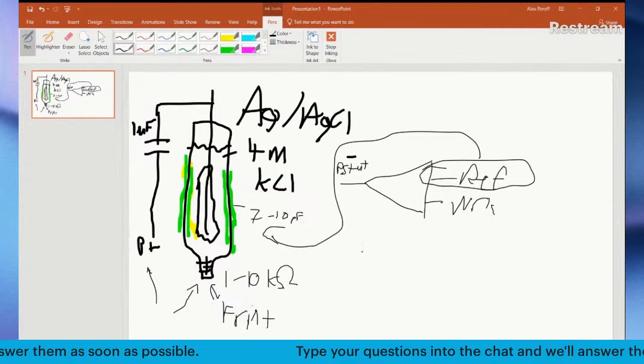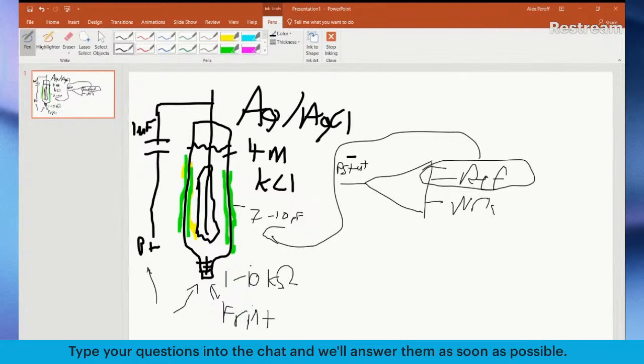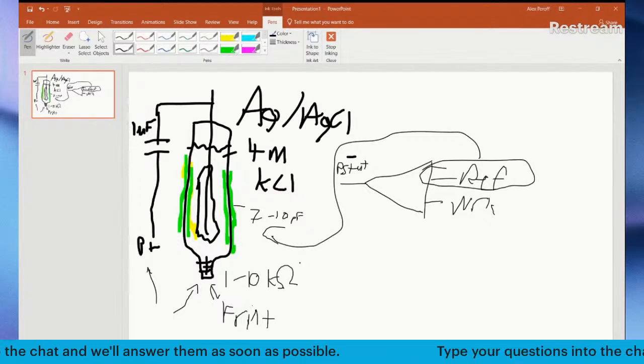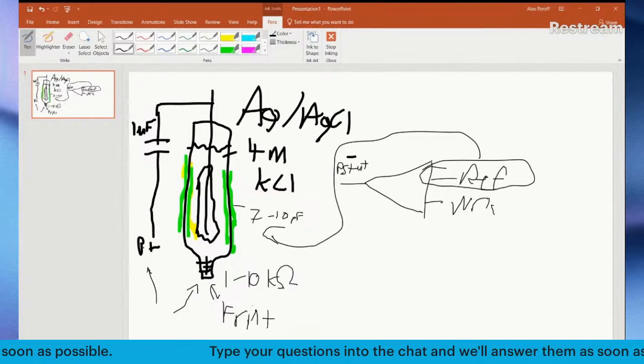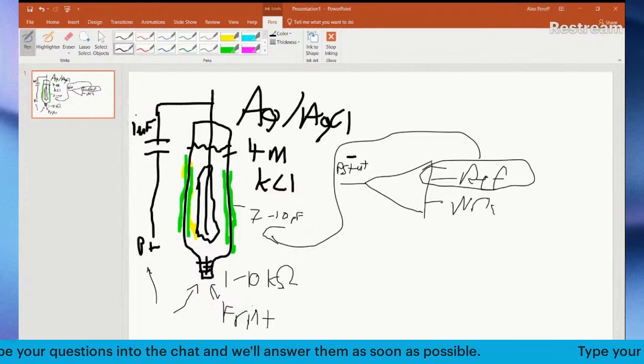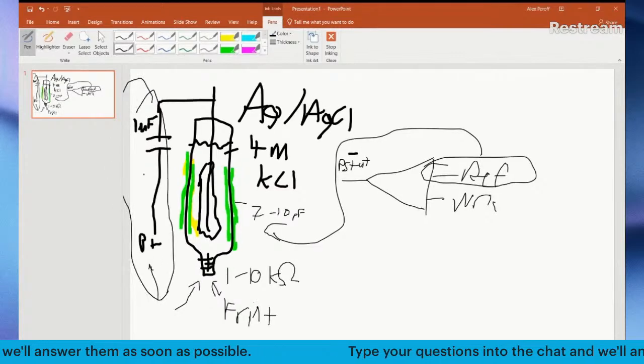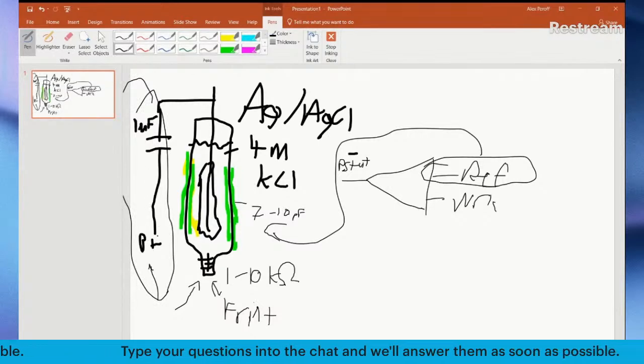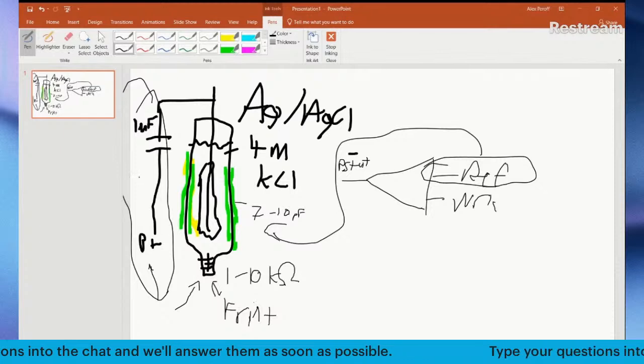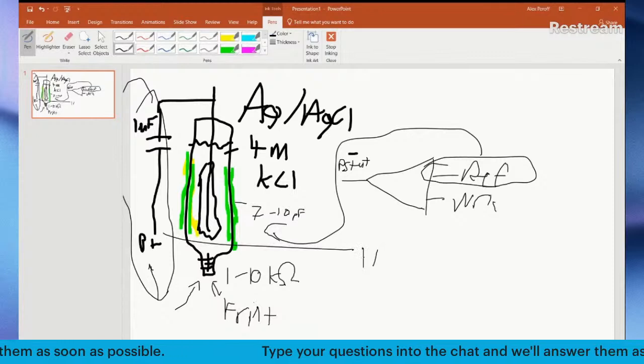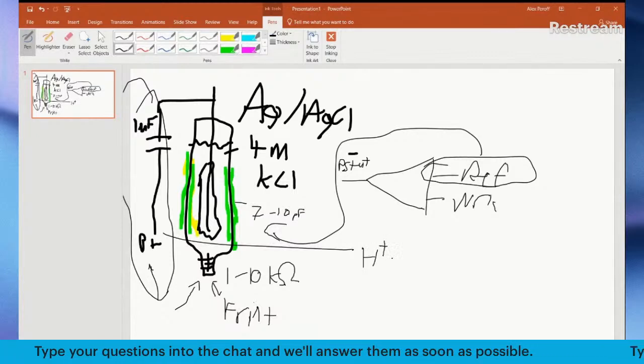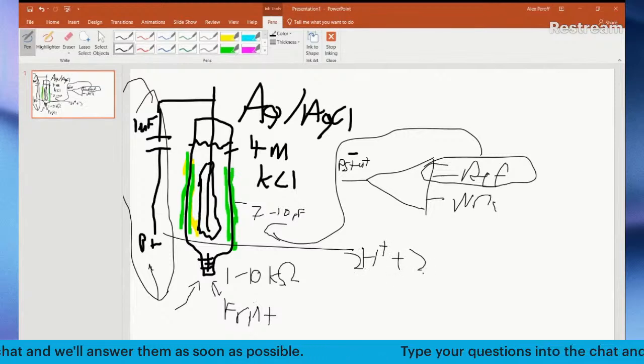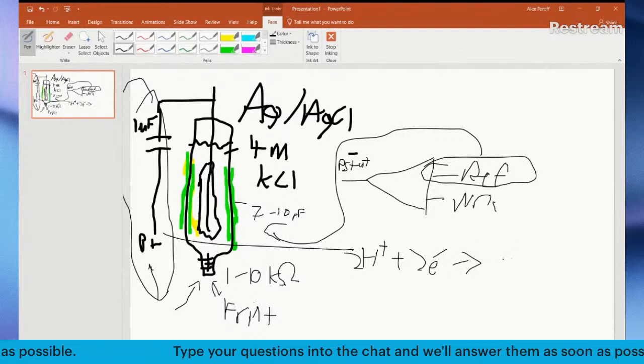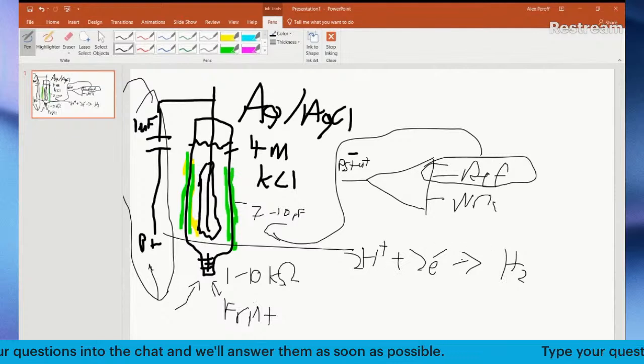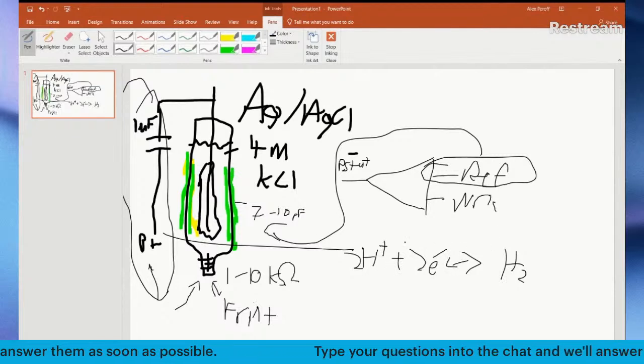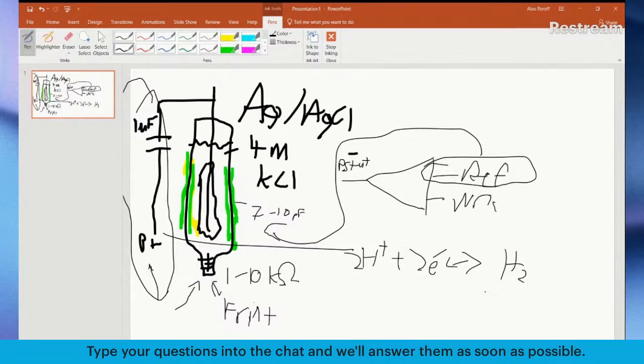and then it moves to a frequency. It collects all its data points, and then it moves to a lower frequency, and that does another sine wave. And so the EIS data that you take at 1 megahertz is going to go through here, and the reference electrode potential is really based on platinum, like this platinum wire and the platinum redox couple, which is most likely your 2 H plus plus 2 e minus going to H2 gas. It might be this redox pair. That's what you're actually referencing at the high frequencies, what your redox potential is.